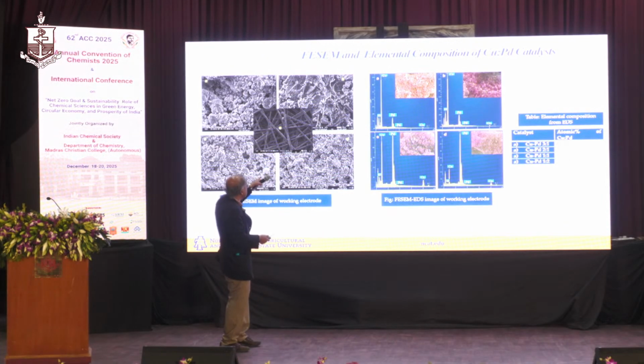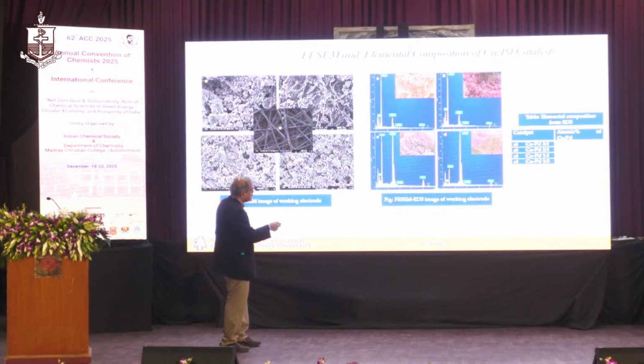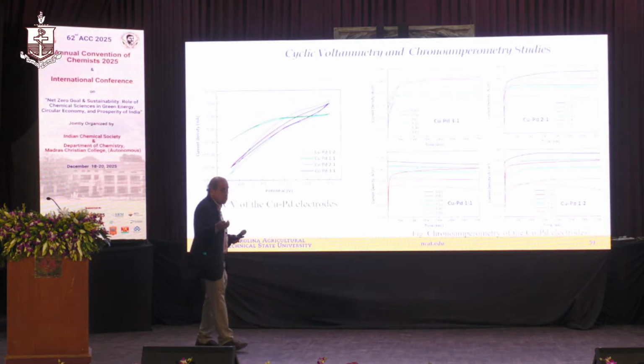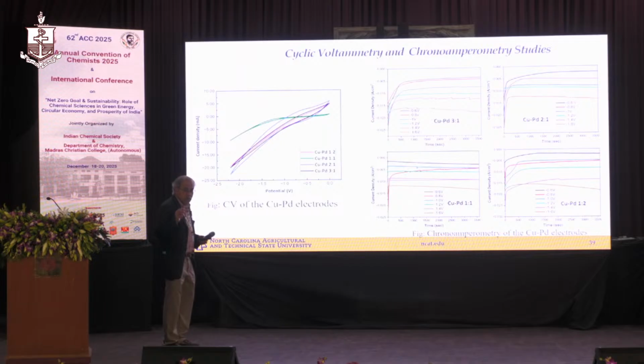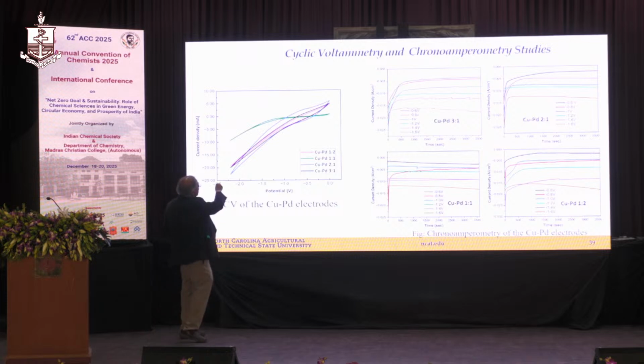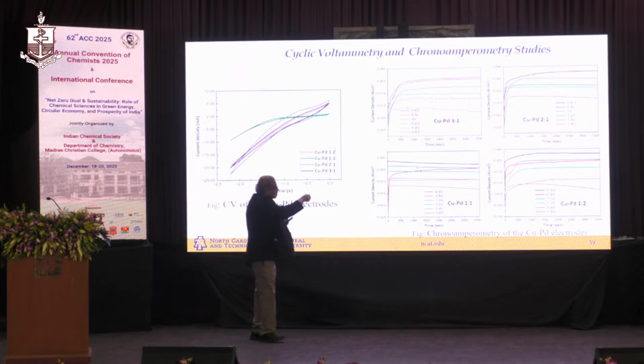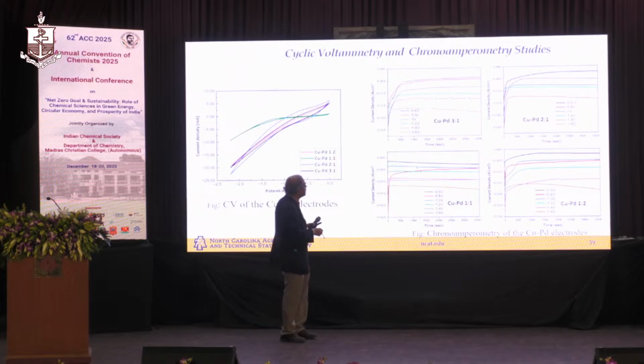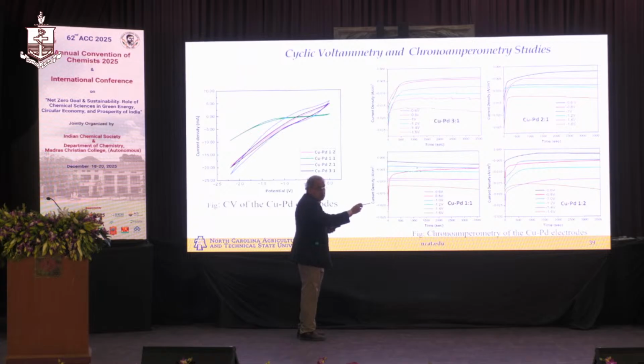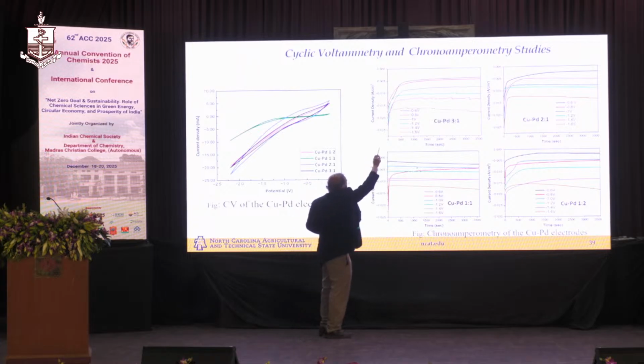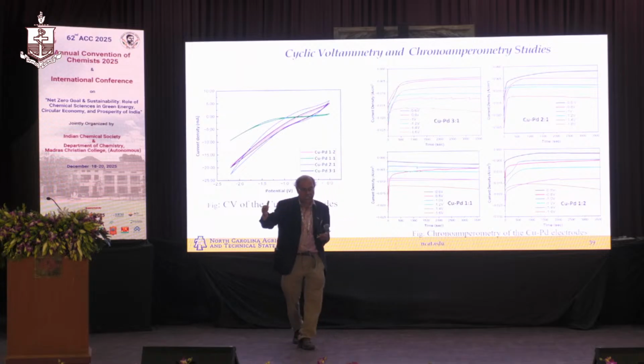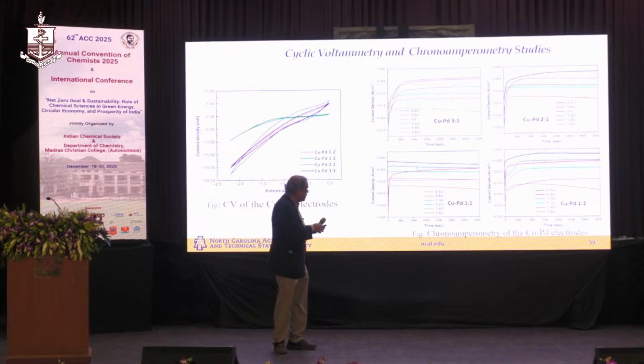Okay, now here are again all these images. This is the atomic percentage of these. This is the EDX elemental analysis for this, and here is the main part. For those of you who are not familiar, this is called cyclic voltammetry, where you plot the current versus the potential, and then you see this. And on the right-hand side, what you see is called chronoamperometry. What it means is you plot the current with the time, and then you can see how all these are behaving. In other words, you change the potential and try to see how it responds. And this is with different ratios of copper and palladium, 1-to-1, 1-to-3, and 2-to-1.